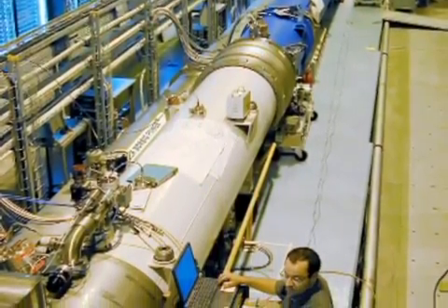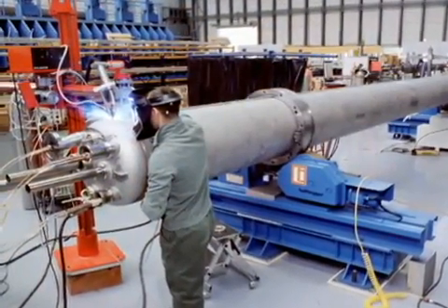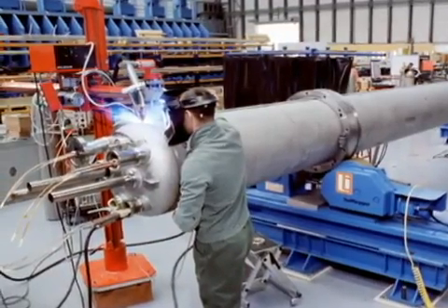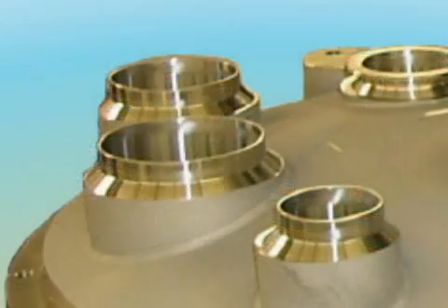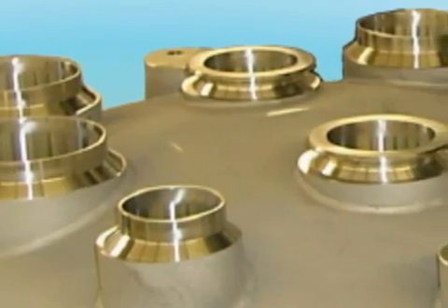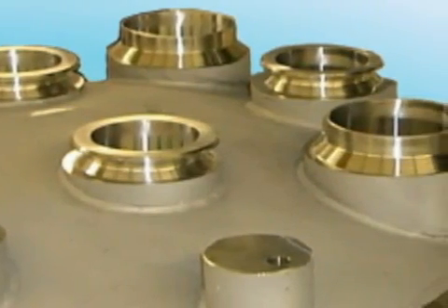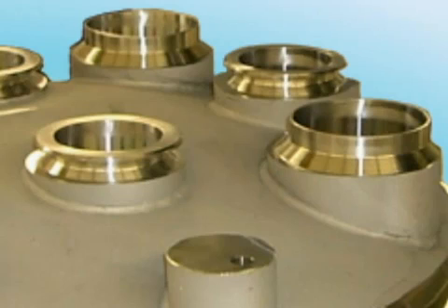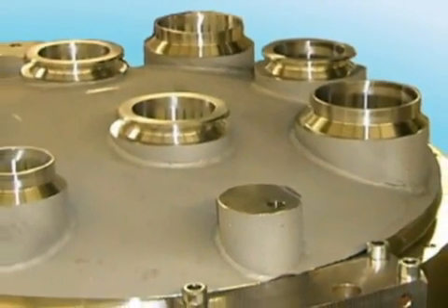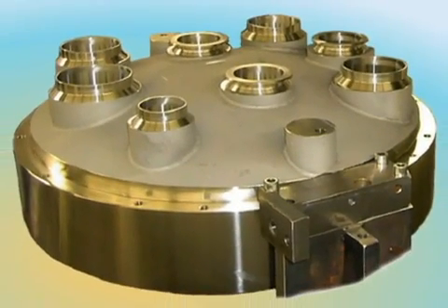The design of the part features several complex configurations. For example, both the inner and outer surface of the broad face is radiused with the inner surface approximately parallel to the outer surface. The exterior of the curved surface has either 8 or 10 projections, depending upon which version of the part is produced. The design differs slightly depending on which side of the dipole magnet it is located. The PM HIPed part meets the equivalent mechanical properties of 316LN wrought stainless steel, including impact toughness and high ductility.